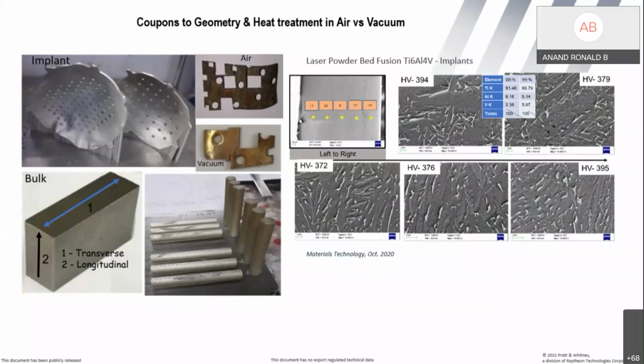Okay, so we have to do some post processing to remove the supports. Yes. Typically, it's very complex. In this, it is easy because the way we build the support structures, they will not be so strongly held. So you can EDM wire cut it, or you can use a mallet and sometimes remove it if accessibility is there. But if accessibility is not there and the geometry requires support structure in very intricate holes, then there is some abrasive polishing that is done to remove the support structures.